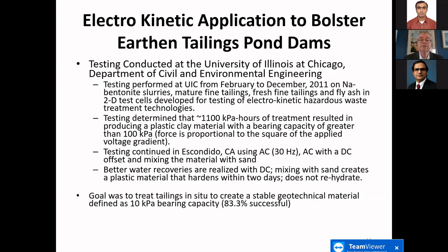Okay, in 2011, we tested the tailings at the University of Illinois at Chicago. The testing performed at UIC from February to December 2011 on sodium bentonite slurries, mature fine tailings, fresh fine tailings, and fly ash in 2D cells developed for testing of electrokinetic hazardous waste treatment technologies. The testing determined that after approximately 1100 kilopascal hours, so that's multiplying the applied power and measured in the number of hours that this is applied, this resulted in producing a plastic clay. So you take this slimy, something with a paint-like consistency, viscosity, and you're able to generate clay balls, in essence.